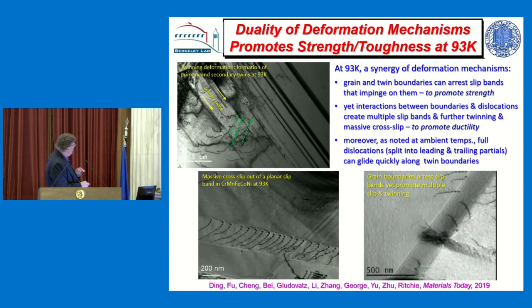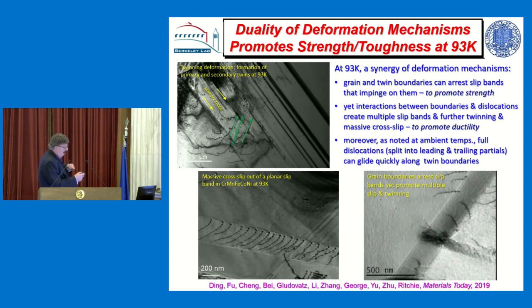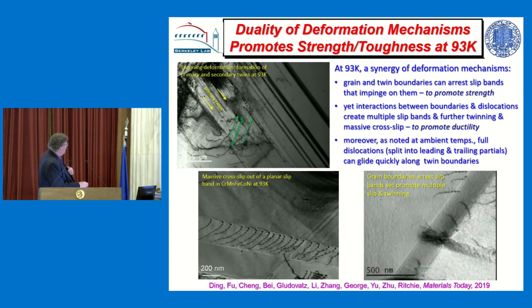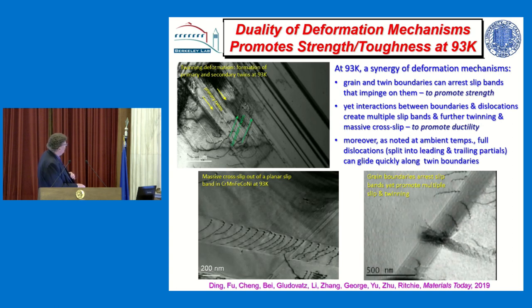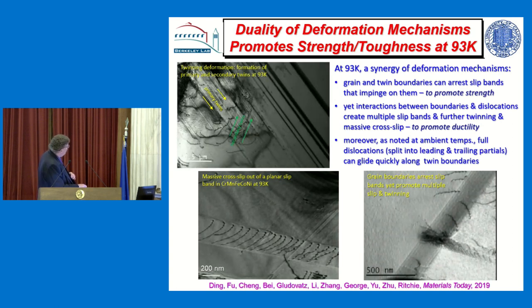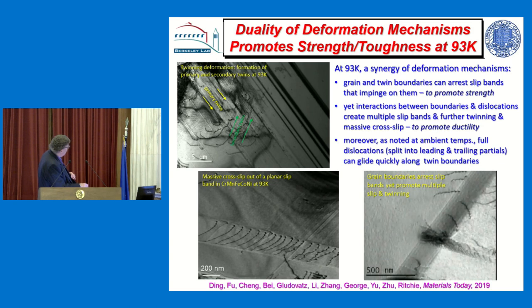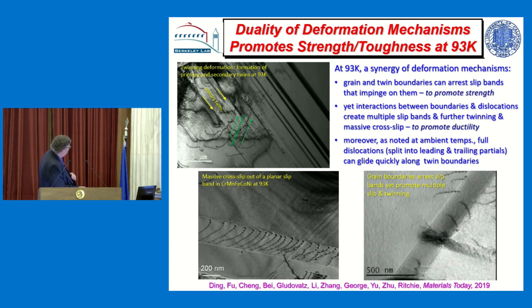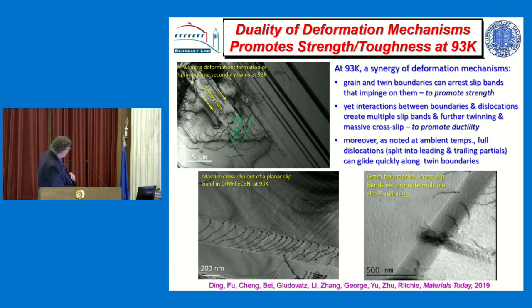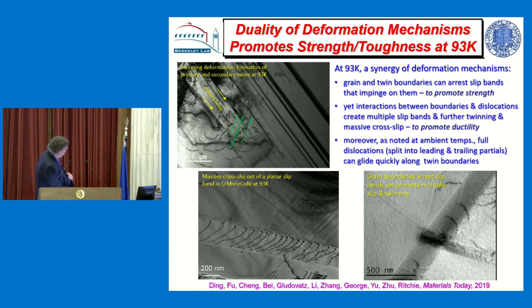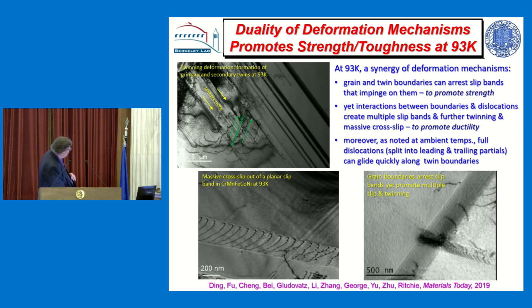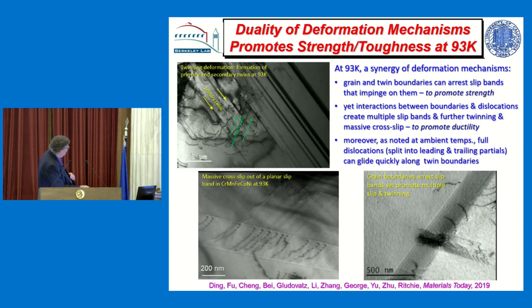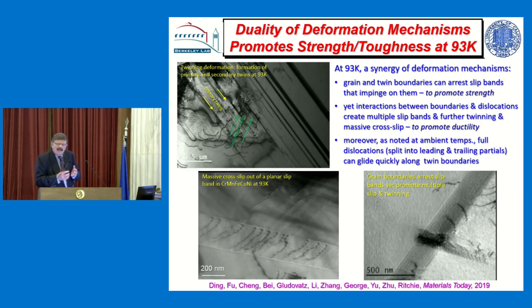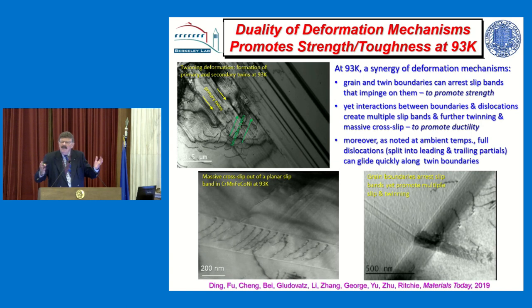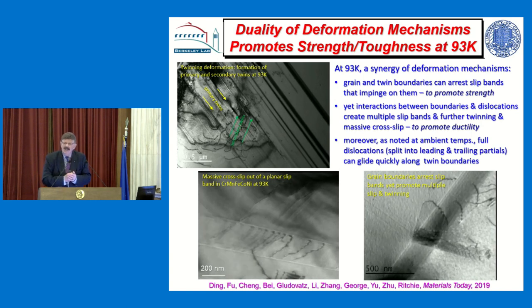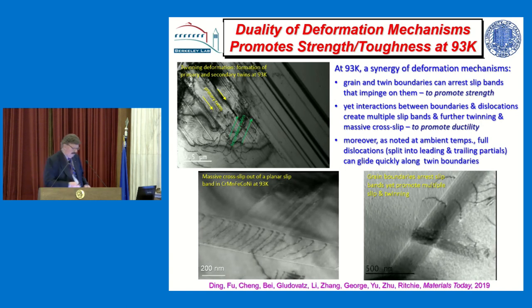There's lots of different mechanisms. These are all transmission electron microscopy images of mechanisms. These are actually done at low temperatures where we can see the twinning where these bands are formed and they twin across. We can see these dislocations moving down slip bands or arrested by slip bands and then generating deformation across them. So there's lots of interesting mechanisms, but the key is we generate strength, we generate ductility, hence we generate toughness.